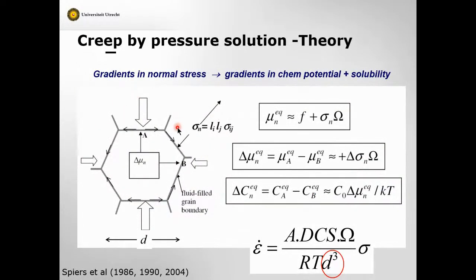And I did a lot of work on the theory of this when I started my career. Indeed, if you apply a stress, this is a crystal inside such a salt rock, then you increase the solubility of these stressed interfaces. Let's say this is the maximum principal compressive stress, this is a minimum. You increase the solubility here relative to here, and so matter dissolves through these fluid films and channels and so on, and it will diffuse and precipitate at these sites. So you get shortening due to mass transport around the grain and then extension in the horizontal direction.